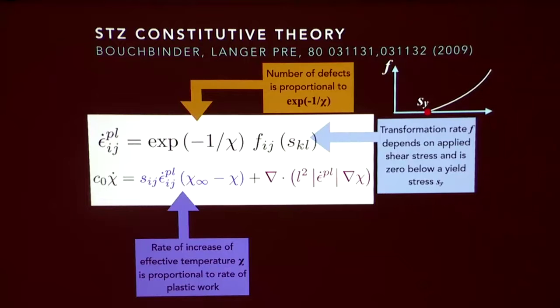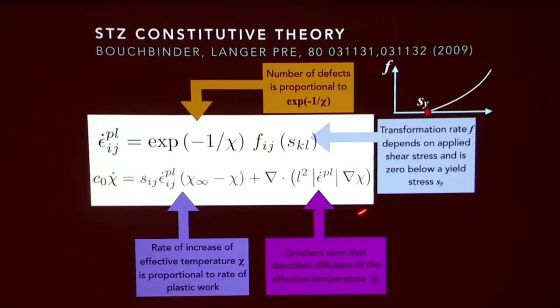And then I have some ability of that temperature field to diffuse, just like a temperature field typically diffuses. The difference here is that the rate of the diffusion constant is also related to the rate of plastic deformation. And there's some length scale that has to come in here that has to be something like the defect size.